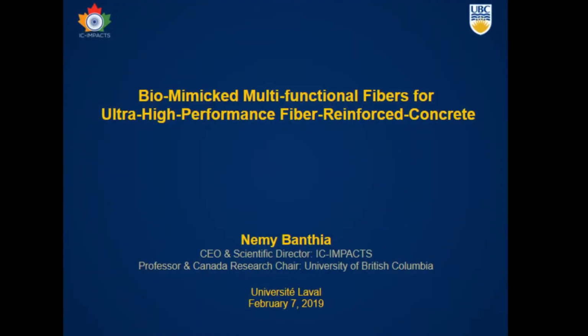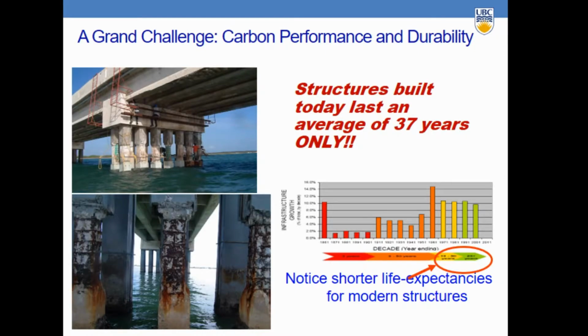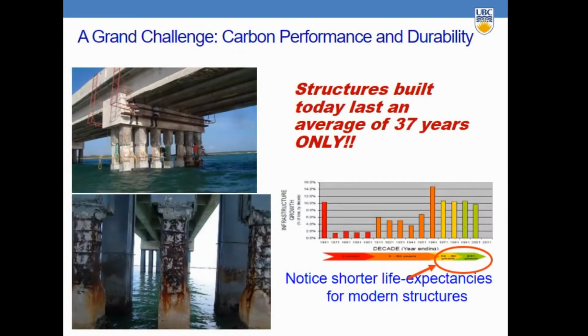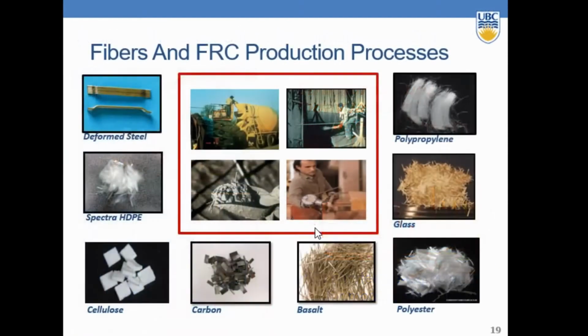I don't know if you've noticed this, but there's a huge issue with deterioration of structures everywhere in the world, and we're always looking for new, better materials that can help us rehabilitate and build new structures with much greater longevity. If you look at our material applications, you will notice that the lifespan of the new materials we're using is getting shorter and shorter. We may be talking about wonderful innovations, but the structures that we build today are actually lasting shorter. According to Statistics Canada, structures are only lasting 37 years, whereas we pretend that we are designing them for 100 years. I think the problem is really in the different types of materials that we're using, and the corrosion and the de-icing salts that are placed on these structures.